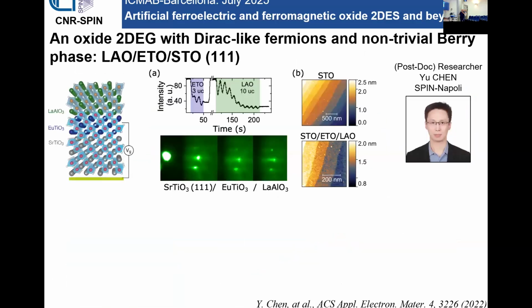Okay, now I will switch to the last part of the talk, which is some part of the activity of Yu Chen. It is about the study of another kind of interface, where we switch the orientation of STO to 111, and we try to introduce spin polarization in the 2DEG by also growing europium titanate in the system.